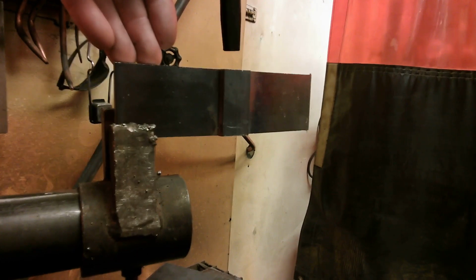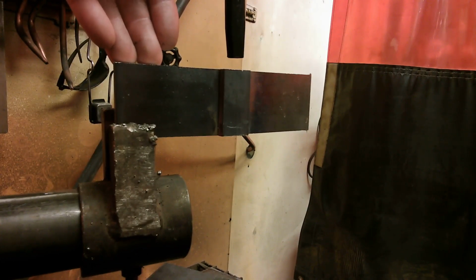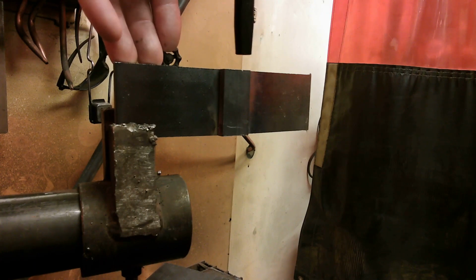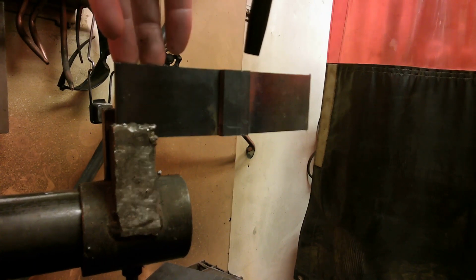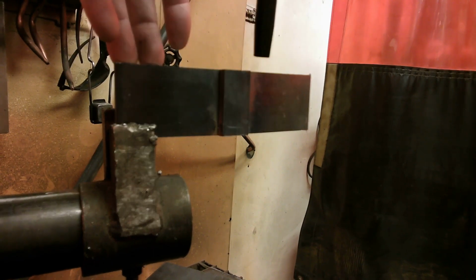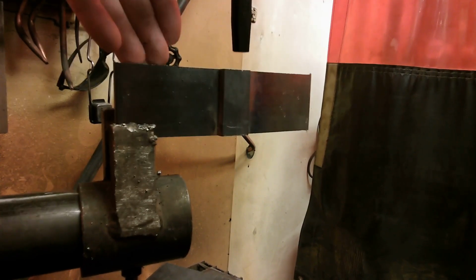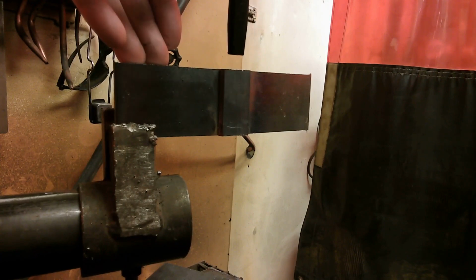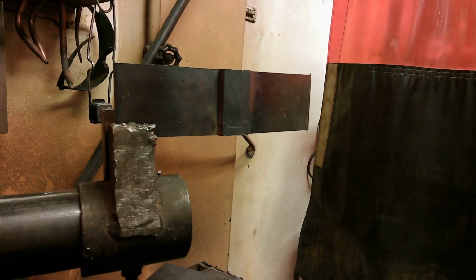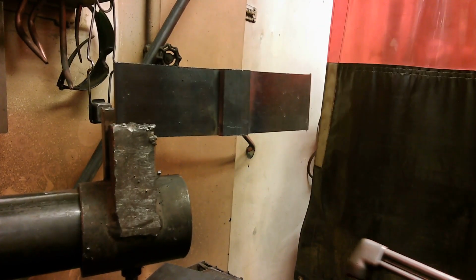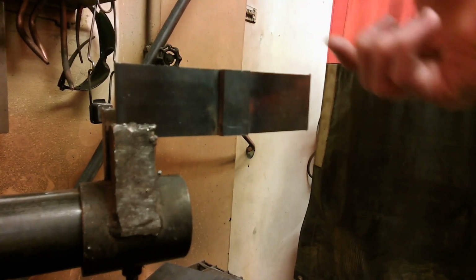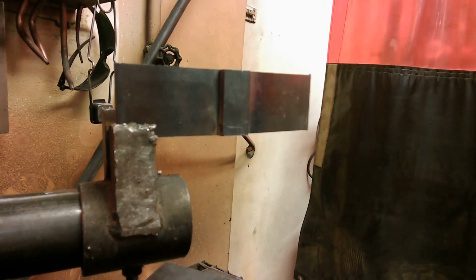If you go too fast, you end up with kind of a hump down at the bottom. That's pretty typical, but I'd rather go too fast and leave a little extra to grind off later than go too slow and gouge into my base metal and ruin a perfectly good bend test. So I'll just walk that. If there's metal on the right or on the left, I can angle it back into the base metal. Just wash that off all the way down. Won't hurt anything. Again, I just don't want to angle back into the base metal during the center of the backing strip. Okay, so this actually happens to be the center piece. I already cut the backing strips off the actual test pieces, so that's why it's a little bit wider.